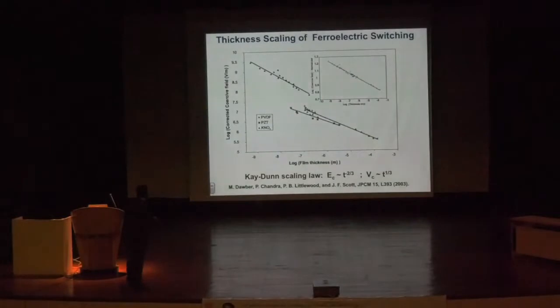well-studied approach called the Kay-Dunn scaling law, where the coercive field goes as T, being the thickness, to the power minus 2/3. That's a problem. And that's shown here with data from a really nice paper that Peter Littlewood, who you know very well, Peter and Jim Scott and a bunch of people wrote. Over a very large range of thickness, it seems to follow this. It was published in the late 50s, early 60s.